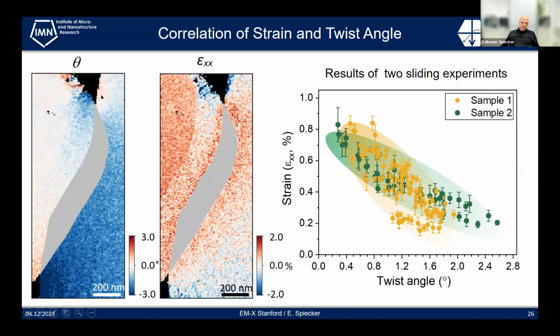If we now evaluate both the twist angle on the left shown and the strain in the monolayer graphene, then we can see that they are correlated. So with increasing twist angle, and this is the result for 2 different samples, one I showed here and the other is an independent experiment, we see that in both cases with increasing twist angle, the strain that we measure in the monolayer graphene decreases.